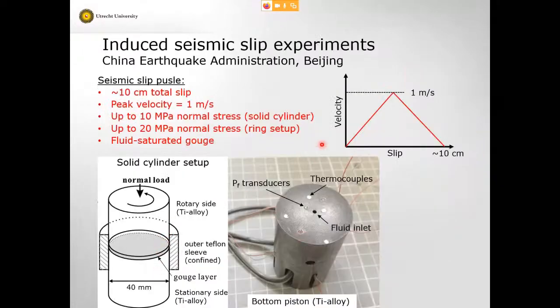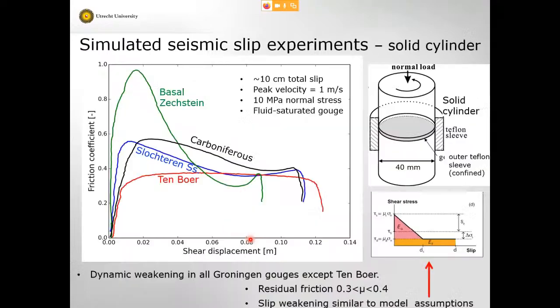We did similar tests, but instead of the huge displacements that you have in natural earthquake experiments, we did slip corresponding to a Groningen earthquake. So 10 or 20 centimeters of slip reaching a peak velocity of about 1 meter per second. That would roughly simulate a Groningen earthquake. We did them under relatively high normal stresses, which is unusual for this type of experiment. And we used the real gouge materials from the field to do these high velocity friction pulse experiments to simulate an earthquake. And what did we find?